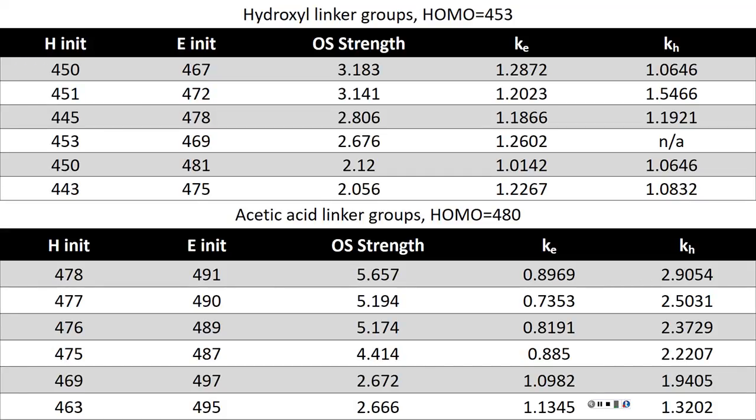You would want a slower relaxation rate to prevent recombination, because if they converge back towards each other extremely quickly, then you've got a much higher probability of them recombining, and then you've lost your exciton, so you don't get any current out of it.